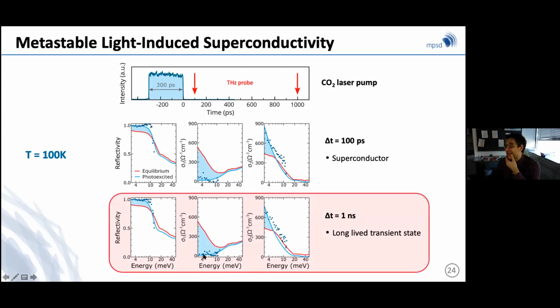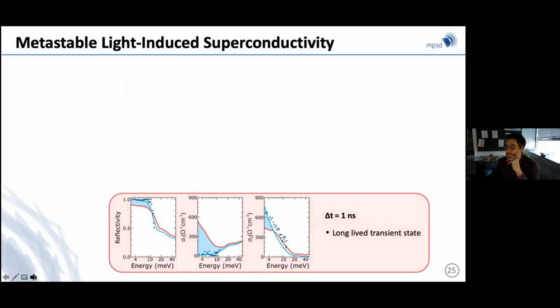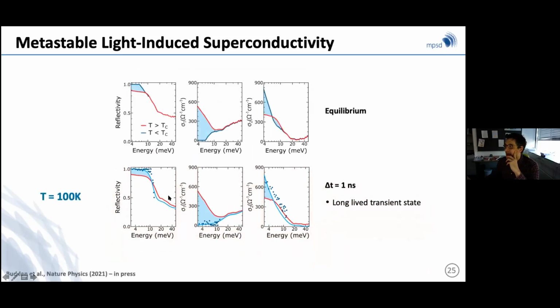If you are thinking that our data is noisy, you should think that this experiment is now done at 13 hertz as opposed to a kilohertz. So the noise of the measurement is a little bit higher, but it was sufficient to convince ourselves that the response was superconducting-like all the way to at least 1 nanosecond. And again, this is sort of an equivalent observation to the one that we reported in the previous paper.